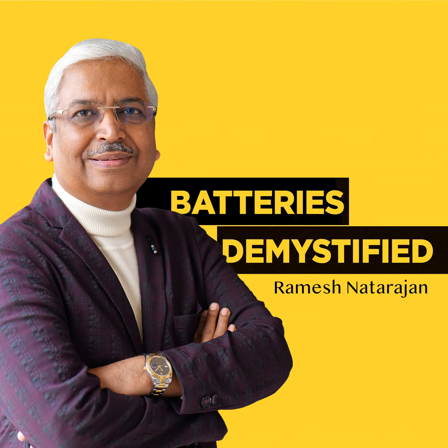When measuring the voltage of 3 cells using a cadmium electrode during discharge, if the total cell cutoff voltage per cell is 1.80 volts, we may have a situation towards the end of discharge with 3 cells exhibiting different values. Let's consider cell 1, which consists of a set of positively charged plates with a voltage of 2.10 volts and a set of negatively charged plates with a voltage of 0.30 volts. The difference between 2.10 volts and 0.30 volts is 1.80 volts.